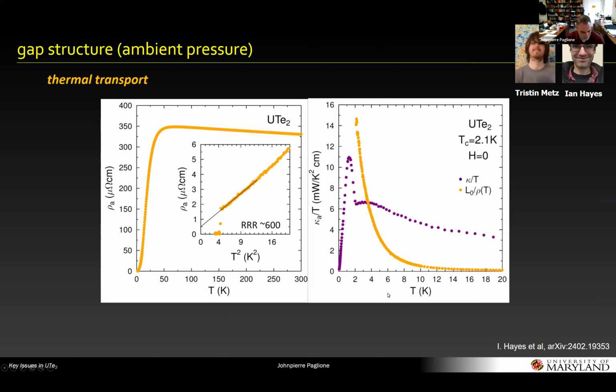All right, so on to our own studies of uranium telluride. We were also doing this in parallel, using these 2.1 Kelvin TC samples grown by tellurium flux. What I noted before, that was pointed out in Ian's paper here, is that we did this for the first time, this tellurium flux growth. Similar triple R's as all the other salt flux crystals and so on.